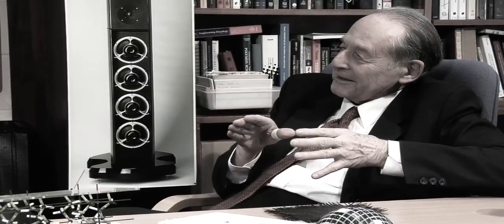If you were just commonsensical, you'd say, well, if I take something like this and put it in a heated press, it'll start melting from the outside. But if you do it carefully, you can get each individual element. If you were looking at the fibre and it was a circle, the whole of the outer perimeter melts, like a ring of molten material. Then, if you do it under a certain amount of pressure, that spreads out, fills all the gaps, so you have a perfect 100% fibrous structure, which is reinforced with the same polymer.